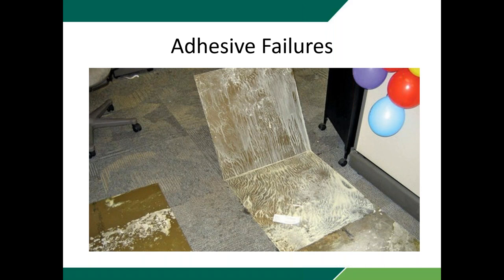So the first thing that I want to talk about here is adhesive failures. So what's changed? Many years ago we didn't have the problems that we're having today with adhesives and compatibility with moisture. And a big part of this came about probably in the mid 90s when the EPA passed a lot of restrictions that changed the way that the adhesives had to be manufactured. They had to take a lot of the solvents out and use more water-based type materials, which led them to be more water soluble. So a lot of times what we have nowadays is adhesives that don't do well in the presence of moisture, where in the past it really didn't have as much of an effect on them.